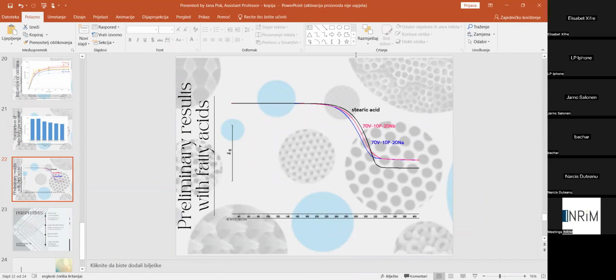And in fact, this is just the preliminary results for the oxidation of stearic acid. Usually, this reaction is not followed by the GC, but it is followed by the TGA analysis. And in fact, what we suppose is that by the time that we are using the catalyst, the temperature of degradation of stearic acid should be moved to a lower value, meaning that in fact the catalyst has its role. These are still the results that should be more researched and will be optimized.